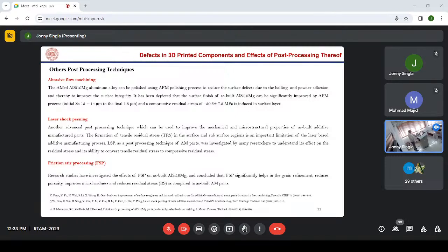Other post-processing techniques, miscellaneous techniques, are abrasive flow machining. This is used sometimes. Laser shock peening is another technique which is used as a post-processing technique. Then friction stir processing, which is now used along with additively manufactured components. We have seen FSP in conventional manufactured components, but in AM also it is used, and it helps in grain refinement, reduces porosity, improves microhardness, and reduces residual stresses on the as-built AM component. In our institute, we have recently purchased an FSP setup, and soon some of the students will be working on this, right?